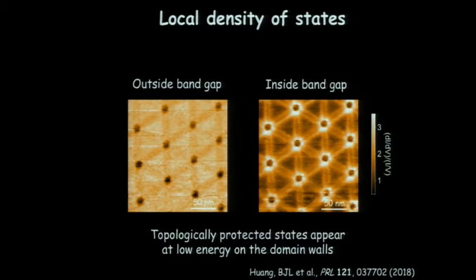And we only see these states when we get to these very long wavelength Moiré patterns. At the sort of 1 degree twist angle, where the Moiré pattern is about 10 nanometers, these states don't appear. It's only when you get down to about half a degree or smaller, on the order of 30 to 50 nanometer Moiré patterns, that these topological states appear, because you need well-defined domains of Bernal stacking with the domain walls in between them. If you go to a larger twist angle, you don't have these well-defined domains where you can see the differences.